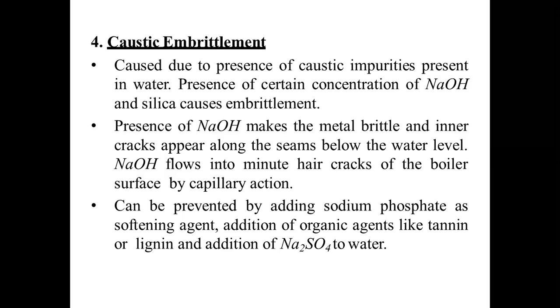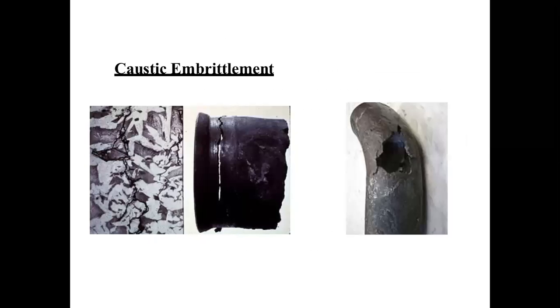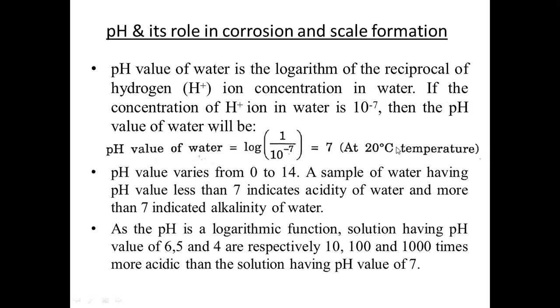NaOH flows into minute hair cracks of the boiler surface by capillary action, and it can be prevented by adding sodium phosphate as a softening agent, addition of organic agents like tannin or lignin, and addition of Na2SO4 to the water. You can see, this is caustic embrittlement. There is a hair crack. This crack will increase and further this will happen.